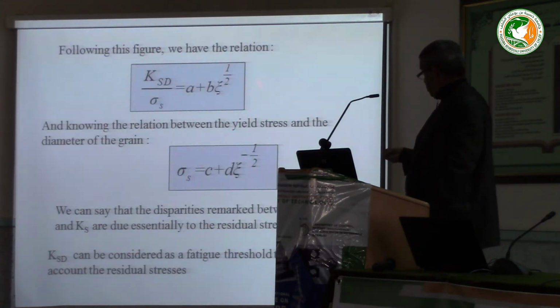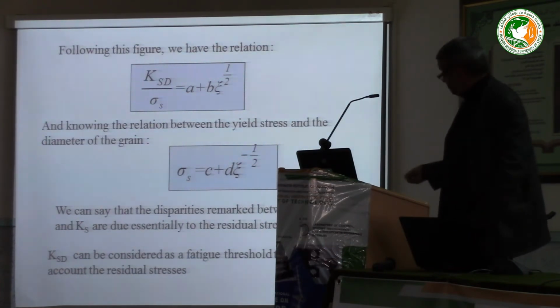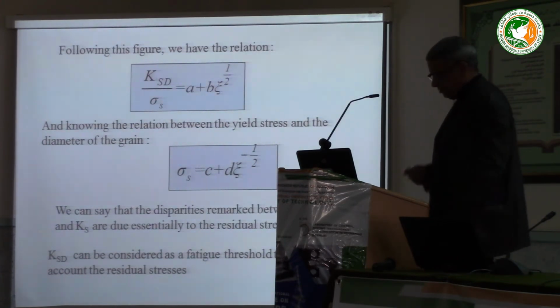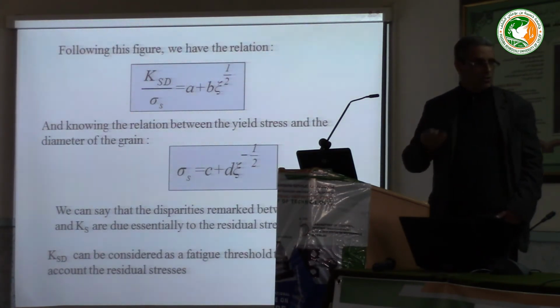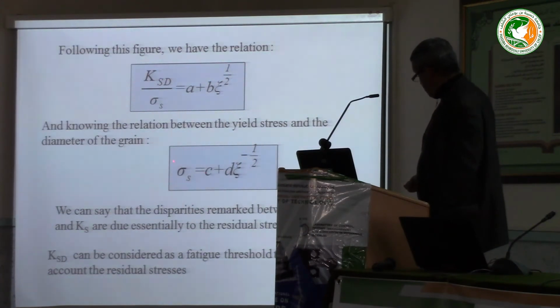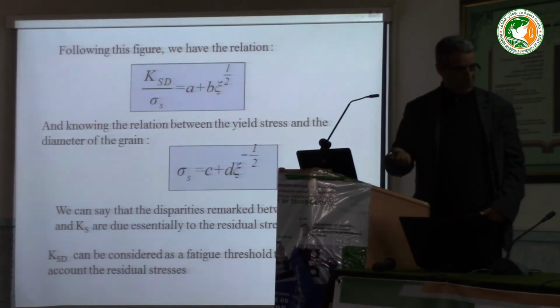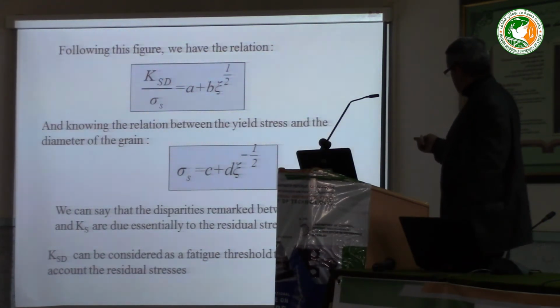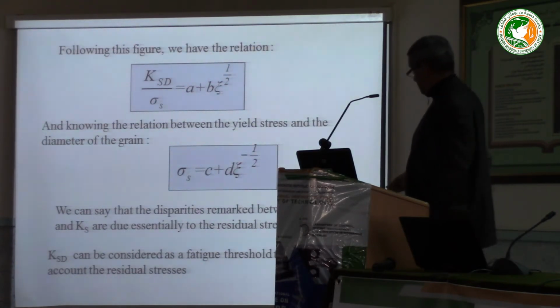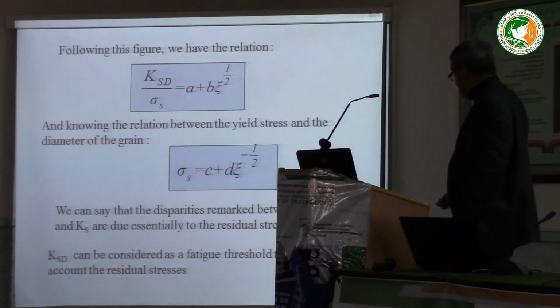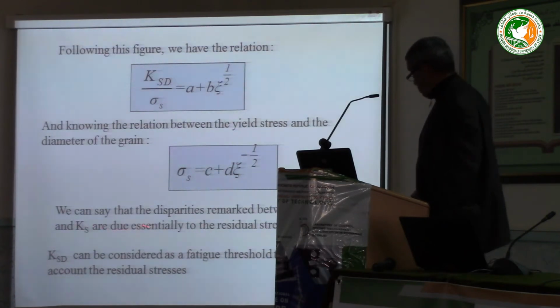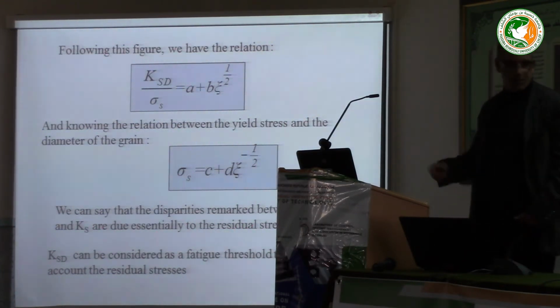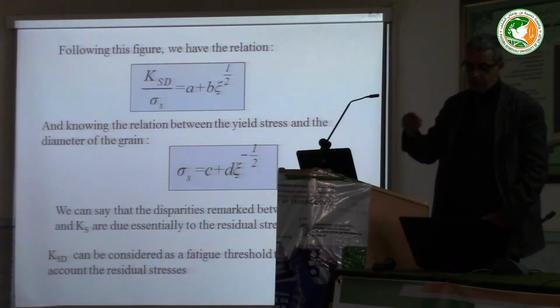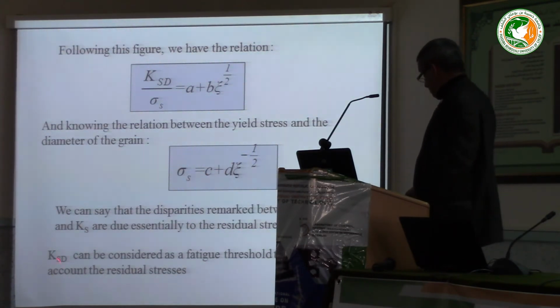Then we have this expression. Knowing that for the material which verifies the Hall-Petch relation, the yield stress varies inversely proportional to the root of the grain size, we can say that the disparities remarked between the KSD and the fatigue ratio are due essentially to the residual stress, because in our work we take into account the residual stress. And KSD can be considered as fatigue threshold, taking into account the residual stress.